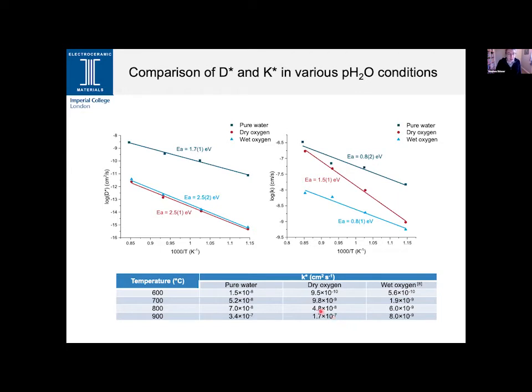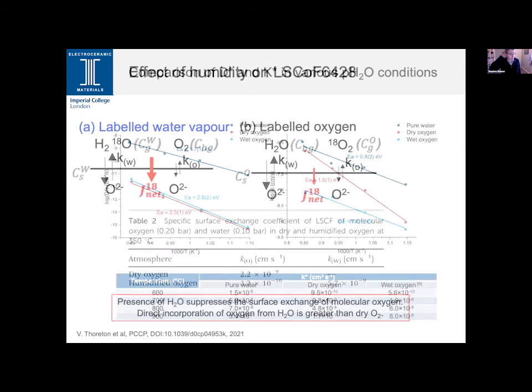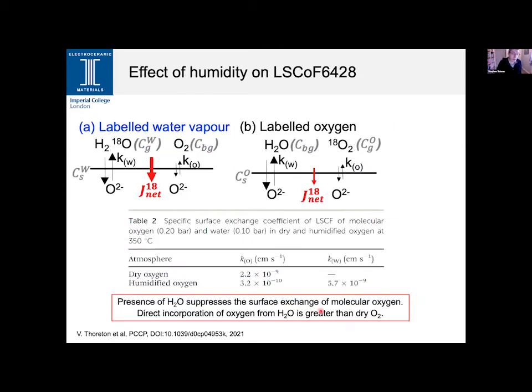So is that an effect that is only seen in these lanthanum strontium chromates? Well, perhaps not surprisingly, the answer to that is no. Some work was done almost in parallel by Vincent Thoreton and John Kilner, which I was not involved with, on a different system at a different temperature. This is looking at the lanthanum strontium cobalt iron oxide system at a remarkably low temperature of 350 degrees C, again looking at the labeled exchange into the ceramic.